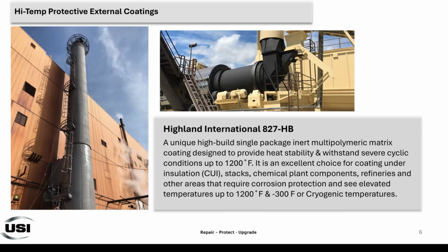And the last product I want to talk about briefly is a Highland International 827HB. This multi-polymer matrix coating is designed to provide heat stability with extreme temperatures all the way up to 1200 degrees F, and is also a good coating to prevent corrosion under insulation, and can even go down to minus 250, 300 degrees F for cryogenic temperature conditions. Sometimes you'll want to use a primer with it, but it can also go directly to metal by itself.